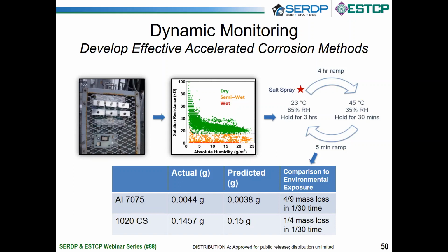In the table below, I would like to point out the most important column here is the rightmost column, where using accelerated corrosion testing with this methodology, we've been able to replicate 4/9 the amount of mass loss in about 1/30 the amount of time for aluminum 7075, and about 1/4 of the mass loss in 1/30 of the time for 1020 carbon steel. And so this is significant in that the main goal, obviously, is to provide representative corrosion in the form of an accelerated corrosion test so that we don't have to rely on outdoor field testing, which obviously takes a long amount of time to qualify or validate new corrosion prevention technologies.